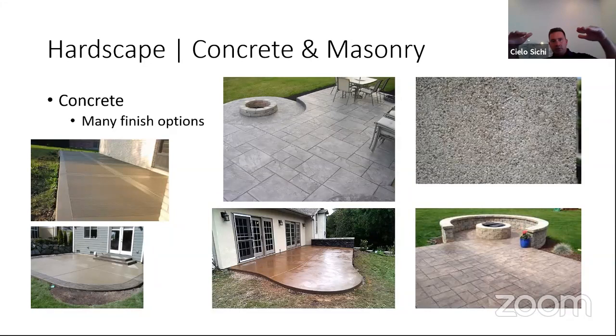And if you have it sealed, then you can tend to get white clouding under the sealer. And if it's not sealed, you get some white clouding and you wash it off. It's called efflorescence. It comes through in the sand or the aggregate. You see it come through in brick a lot. You get a lot of efflorescence in brick. And it doesn't last forever, but you do have to clean it off, or you appreciate the aged look of it. If it's sealed, then you end up with this cloudy appearance under the sealer.